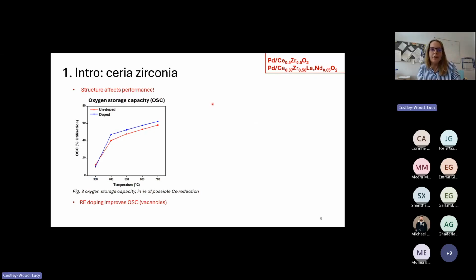So for the bare ceria zirconias, as I said, the doped material has a slight performance increase, and that's because whilst cerium and zirconium in their oxidized form are in 4+ oxidation states, the rare earth metals are 3+, and this means we have oxygen vacancies in the structure. This doesn't mean that we can remove and replace more oxygen because of these vacancies, but they are fixed vacancies, and it means that the oxygen that is being removed can diffuse much more easily through the structure.